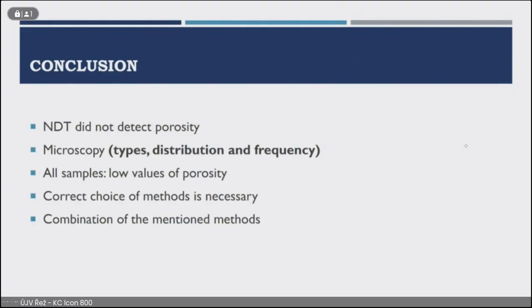Also, I'd like to mention that microscopy did observe pores with sizes in range from 1 to 10 micrometers, which means these values are lower than the distinguishability of X-ray testing or ultrasound testing. Also, all samples had relatively low values of porosity. I'd like to mention that this topic was continued by my leaders, Mr. Beneš and Mr. Bricin, and they created some papers.